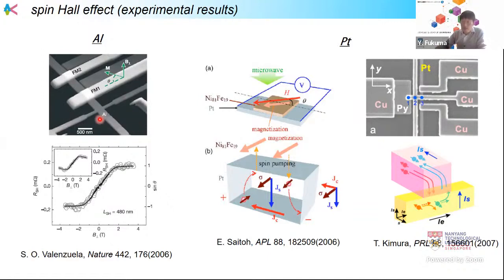What is important in this configuration is that the direction of the charge current, spin current, and the polarization of the spin should be orthogonal to each other. That's why we rotate the spin polarization from in plane to out of plane by using the magnetic field, and we can detect the signal like this. But in the case of aluminum, as you know, this is a lighter element. That's why it has weak spin orbit interaction. Only at the lower temperature can we observe the spin Hall effect signal. But when we use platinum, platinum has a strong spin orbit interaction. That's why we can get a really clear signal, even at room temperature.